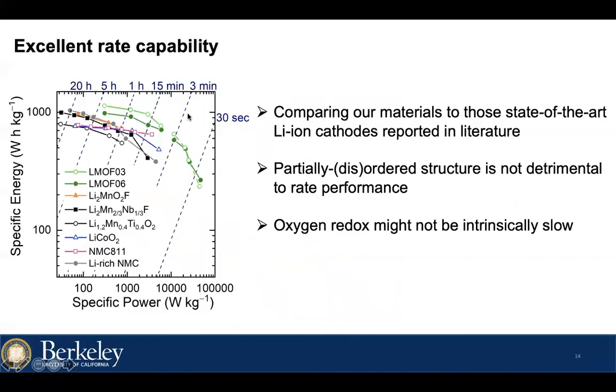We also make this Ragone plot to compare our materials with other state-of-the-art lithium-ion cathodes, such as lithium-excess DRX materials and layered materials like lithium cobalt oxide, NCM, and lithium-rich NCM. And this data are the highest rate performance we can find in the literature. It turns out that our material can achieve the highest energy density at the same current density. And this result is pretty remarkable, especially when we consider our material has a partially disordered spinel structure and heavily uses oxygen redox, which are both regarded to have a negative effect on the rate performance.